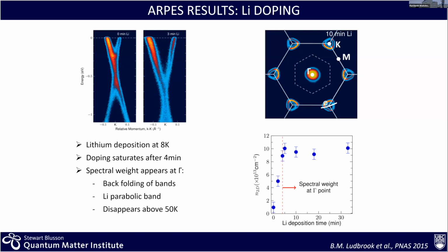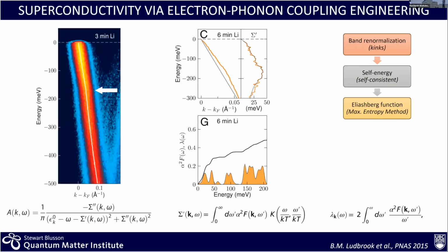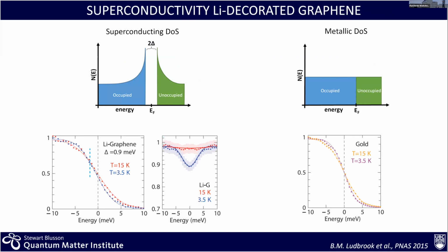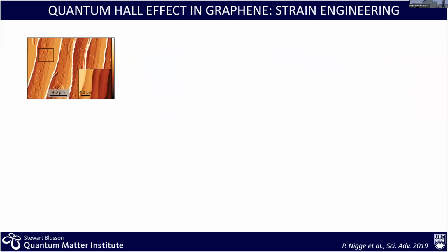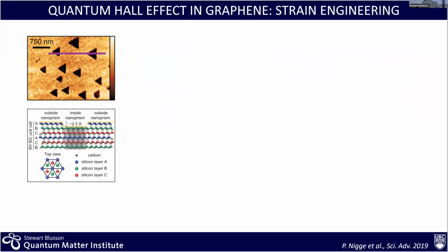I think so. I would say it is highly unlikely. I can tell you an anecdote after, but basically, if you really look at this object, the system likes to have those defects. They are all triangular, of comparable size. It's a distribution in size, but very well centered around 300 nanometers, and it's just one monolayer of defects, and this happens during the growth. Now, how would you go into a hexagonal type shape? I have no idea. How would you first force the system to do that?